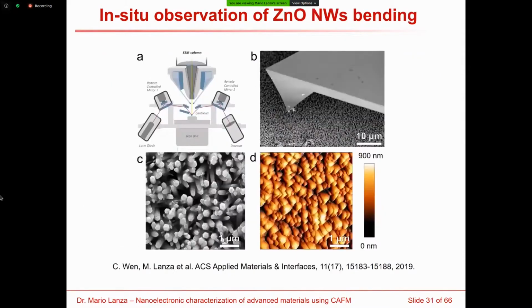And the second example that I wanted to highlight is the introduction of one conductive AFM inside the chamber of a scanning electron microscope. Here you can see the SEM image of the tip contacting one sample that consists of zinc oxide nanowires. And in panels C and D, you can observe the pictures taken by the SEM and by the AFM of the same nanowires. So this is something interesting because, again, we could correlate the electrical signals with the image obtained by the SEM.